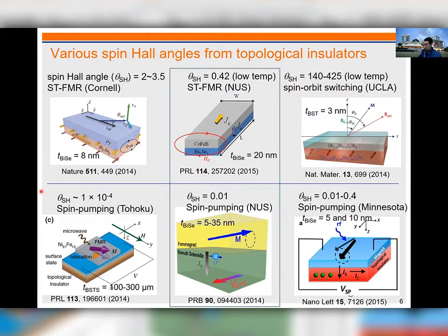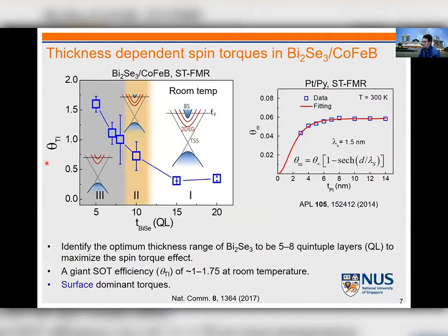that thickness plays a very important role. For example, the small value comes from a bulk sample of hundreds of micrometers, and then other people used tens of nanometers. If you look at those two reports from my group, some people used several nanometers, down to 3 nanometers, and you can see some kind of correlation. If somebody uses very thick films, the efficiency is low. If somebody uses thin films, efficiency increases. Of course, there are some other roles which I'm going to discuss later on.